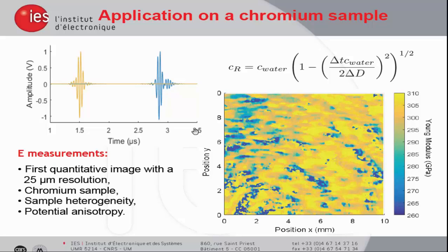So the image is, how can I say that, maybe less elegant, but in fact it reflects the heterogeneity of the chromium sample and the anisotropy of this sample. Again, it's a 10 by 10 millimeter squared image with a 25 micrometer resolution, and it's the first quantitative image of the Young modulus of the chromium sample. Sorry, it's the quantitative elasticity imaging. Each color corresponding to a value of the Young modulus.